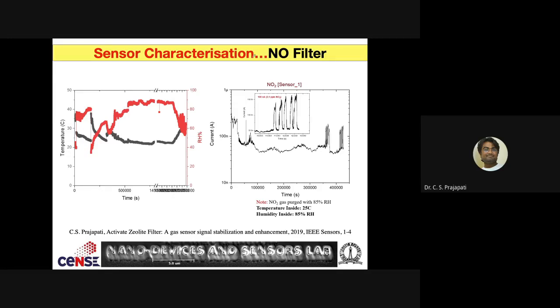So here we have the no-filter data. There is no filter, only the sensor, and we expose that sensor. We recorded the humidity, and you can see the humidity going up and down here, many days of data. We see that the baseline keeps fluctuating up and down a lot. Initially it was fine, and then we exposed 3.1 ppm NO2 and saw how much change comes. It's like a 100 nanoampere change in the signal. That's an indication of the 3.1 ppm NO2 presence in that air.